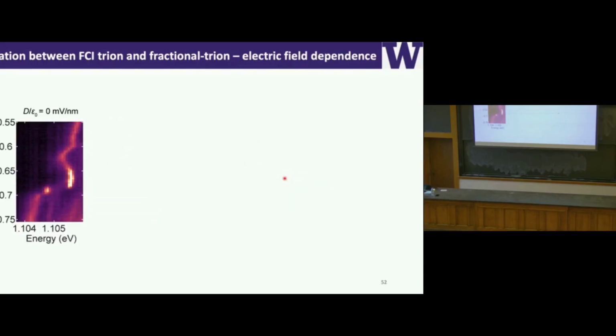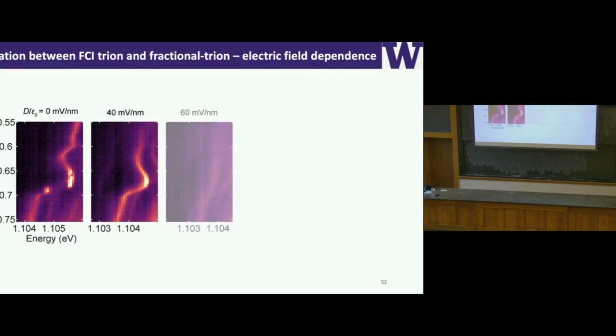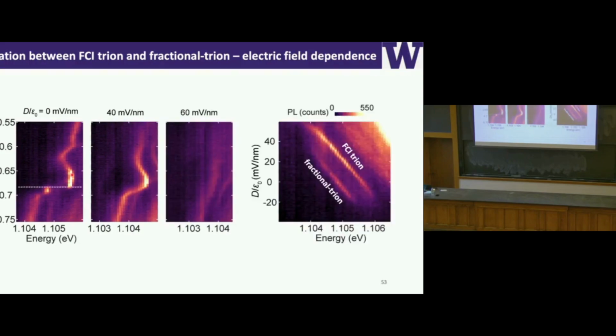So how do we know, right? There are many checks we've done. The first is the electric field dependence. And what you see is the zero electric field, right? Here's zero electric field, and on the vertical axis, the filling factor, I see this fractional trion with this plateau feature. As I increase my electric field, you will see that the two states actually disappear. So if I focus my filling just at the transition from the FCI trion to the fractional trion, and I plot it as a function of a continuous tuning of the electric field, with the horizontal axis being energy, you will see that this fractional trion has a similar electric field dependence to the FCI trion, but disappears first, before the FCI trion disappears. So what it means is that the formation of this fractional trion actually requires the protection of the FCI gap. Okay.